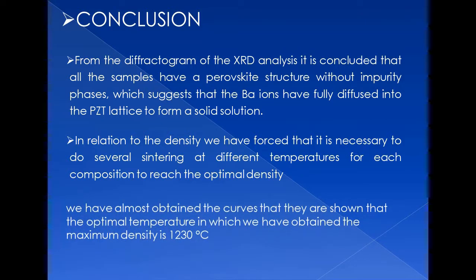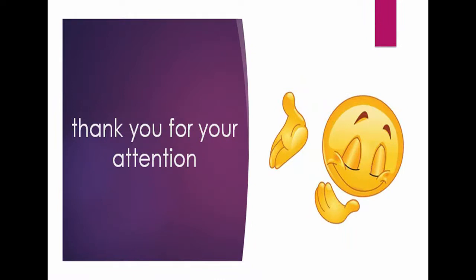We have almost obtained the curves that show that the optimal temperature at which we have obtained the maximal density is 1230 degrees Celsius. Thank you for your attention.